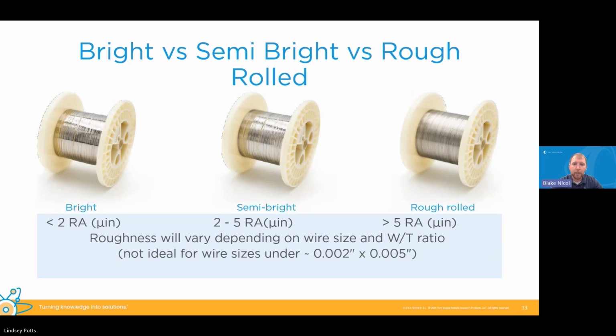Then we have semi-bright, which is just a little bit more dull. You can even see in the picture that, side by side, there's not that much comparable difference. Where you see it is under the scope, under higher magnification. With rough rolled, you'll start seeing that dull appearance on the wire. Talking about some of the RAs, our bright is typically under 1 RA, but with all wire sizes, it's usually under 2 RA. Semi-bright is in the middle, 2 to 5 RA, and rough rolled is typically over 5 RA.